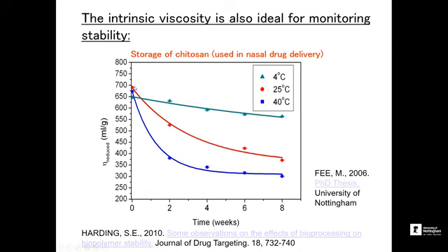At 25 degrees, room temperature, warm room temperature, there is this degradation here, more dramatic than if we kept the material in the fridge. And say if we were in an airport in Saudi Arabia or something where it's 40 degrees, or in the south part of Spain, then this degradation is much more dramatic, but you can see how it bottoms out after it's degraded so far. It bottoms out.